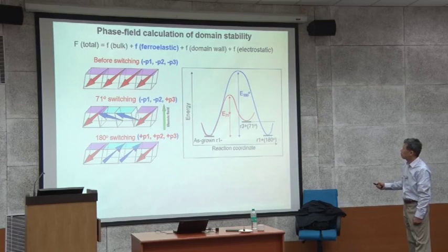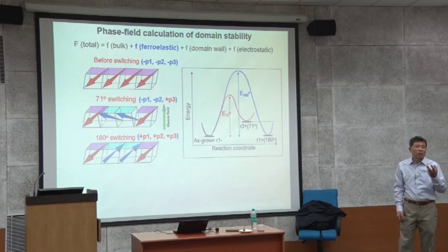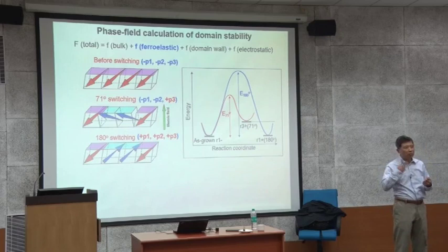But in between, you have 71 switching go to this state. Okay, this state. And over time, this one goes to here. Because initially, going to this state directly consumes a lot more energy than the two-step process. Okay, so this is the actual switching process, a two-step process. When you read a lot of papers about bismuth ferrite, they said 180 switching, 71 degree switching, they have a lot of those words in there.